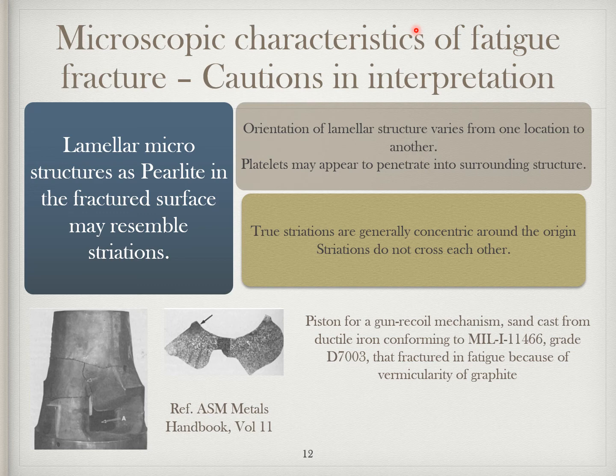Scanning electron microscope views of the area of final fracture revealed dimples in some region and features resembling cleavage facets in others. However, what appeared to be facets may have been interfaces of pearlite lamellae oriented nearly parallel to the direction of crack propagation.